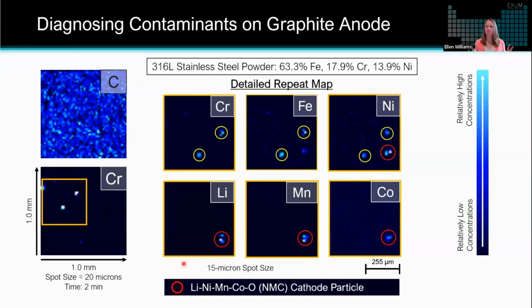And again, because you have the advantage of measuring the full chemistry down to the parts per million constituents, you can get a very detailed picture of what your material is that can be very helpful when you're trying to figure out, okay, yes, I know I have a contaminant here. I identified it with an optical technique, but what actually is this? Which tool did this come from? And that's where this technique adds a lot of value, is by giving you that full chemistry picture of that contaminant, helping you diagnose where it came from and prevent it from occurring in the future.